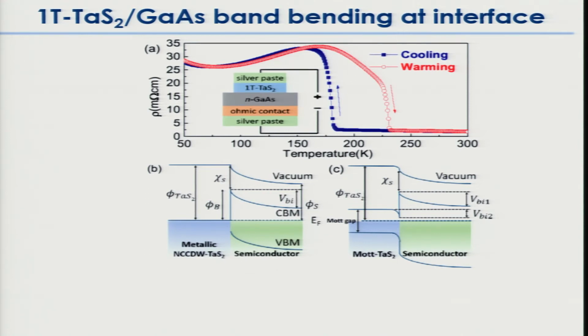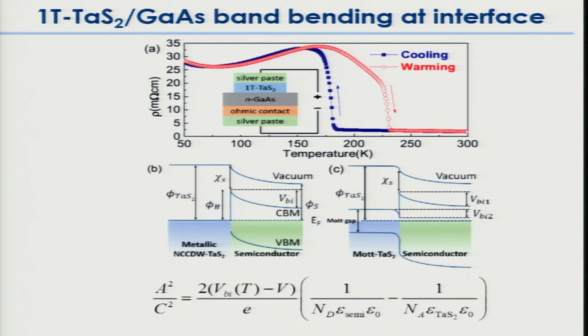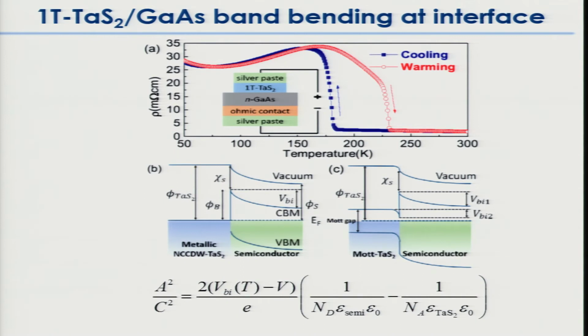But remember, there's a Mott gap that's opening up as you cool it down, so the band structure becomes a little more complicated because there are two built-in potentials to measure. But that relationship that I told you about, the built-in potentials being the difference between the work functions of the two materials, still holds here. It's a PN junction, if you want to think of it that way. And this is the capacitance for this structure, the inverse capacitance relationship. It goes like VBI. This becomes 0, extrapolates.